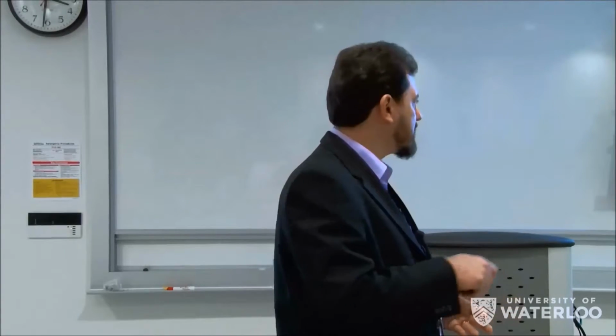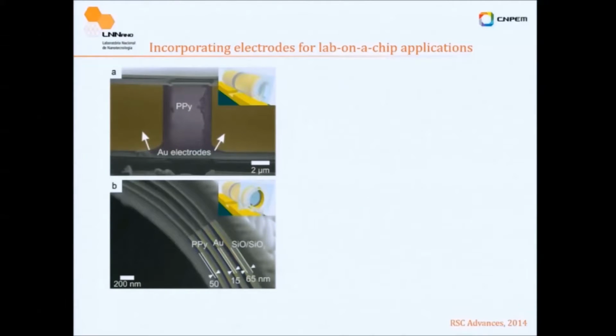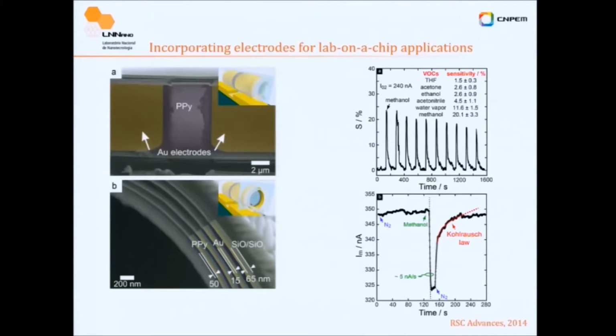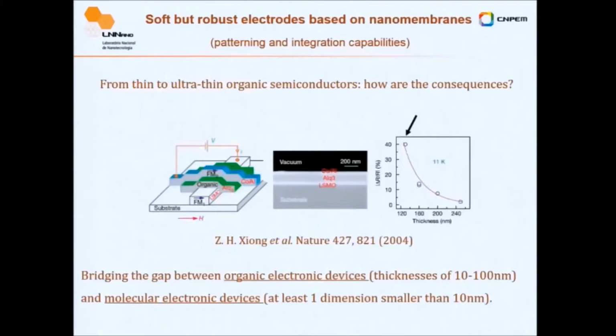If you'll be able to remove the tube and make a top-down contact, you can try a transport in the case of several semiconductors. Here's a metal, it's not that attractive, but nevertheless, it's a type of hybrid structure. We tested different vapors, and you could see really that the material reacts very well. We didn't try liquids here, basically by our incapacity to generate microfluidic devices by that time to inject fluids inside of the tube. So we also investigate the relaxation process when the gas leaves the system, and still there is a lot of things to do.